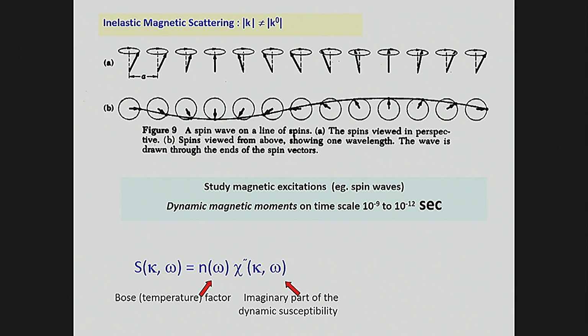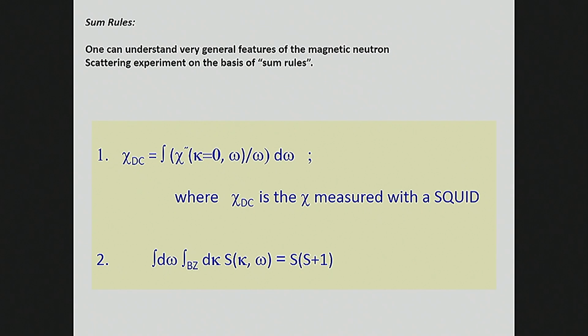And so these spin waves are a lot like phonons now. They can have different wavelengths, different wave vectors. And if you make their wavelength shorter, they'll be a higher energy state, because their underlying Hamiltonian minimizes the energy by having the spins point parallel to each other, or anti-parallel for an antiferromagnet. So if you make this wavelength shorter, you cause the spins to rotate more from site to site, and that gives you a higher energy spin wave. Okay, so that's the way in which you would calculate or measure the elementary spin excitations of the magnetic structures.